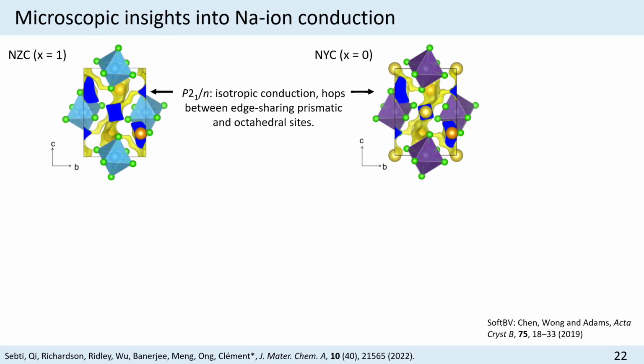So just to recap, we have 2 members that are both able to form this P21/n structure. We can gain some insight into sodium diffusion pathways by using this softBV software, which is a bit of a crude model, but it still gives you some information about what paths sodium ions could take in this crystal structure. And what you find is that in these 2 crystal structures, you can have isotropic sodium diffusion. For NZC, you have some sodium vacancies, no sodium vacancies in the case of NYC.